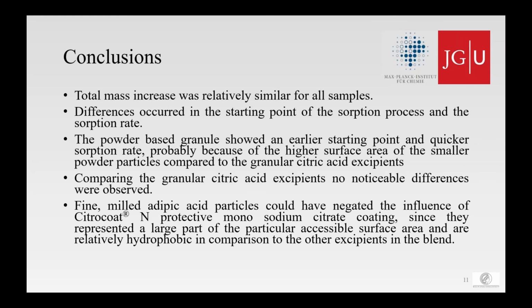And regarding the granular excipients, there were no noticeable differences. One possible explanation that we concluded was that the moisture protective coating of the coated granulate was probably negated, because in the mixture there was also milled adipic acid of very fine particles, which would have represented a large part of the accessible surface, and this is in comparison a relatively hydrophobic excipient. So for the granulates, there was not a big difference.